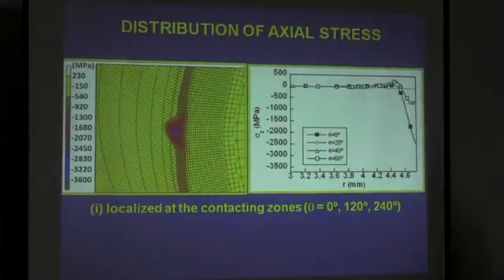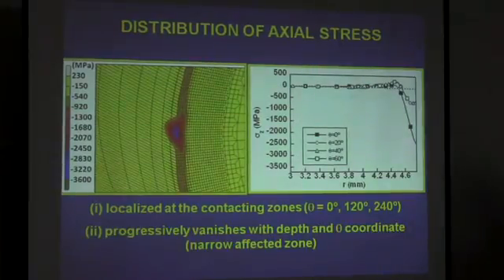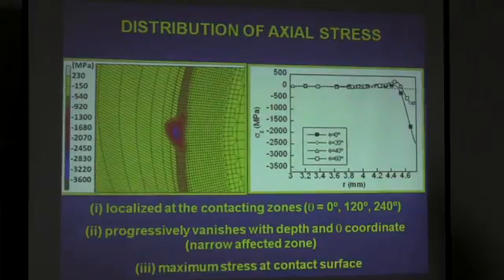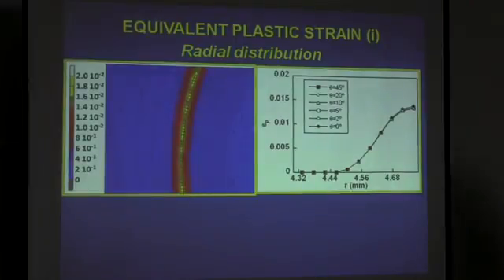In this case, it vanishes with the increase of the angle, and also with the distance to the contact point. Progressively vanishes with depth and θ coordinate, narrow affected zone, and maximum stress at contact surface. Let's go to the strain.